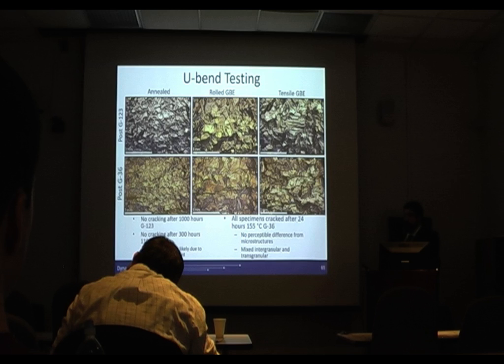And finally, circling back to the questions that we had earlier. Does the grain boundary play a role in the corrosion resistance of grain boundary engineered steel? Yes. It's for each individual grain boundary segment. As they curve or facet, every segment with a different grain boundary plane will have different corrosion resistance. How do corrosion resistant grain boundaries affect corrosion resistance? Resistant segments arrest cracks. So in the TRDs you actually end up with crack arrest and they drop out as whole units.